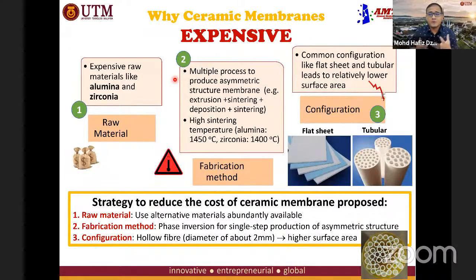So this is one of a few reasons why the ceramic membrane is expensive. Firstly, it is because the ceramic membrane is made from expensive material. Alumina and zirconia are very expensive. It's probably 10 times more expensive than the polymeric material. And also the steps to produce this asymmetric structure are multiple steps, as I just showed to you just now.